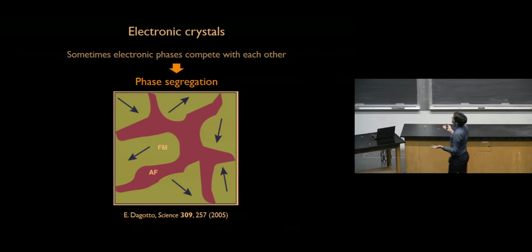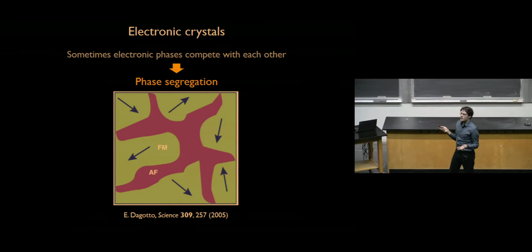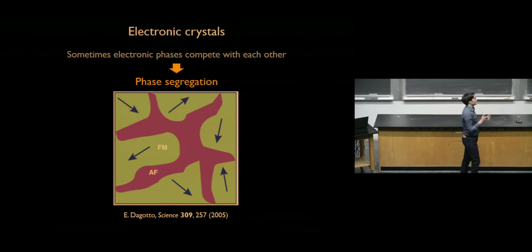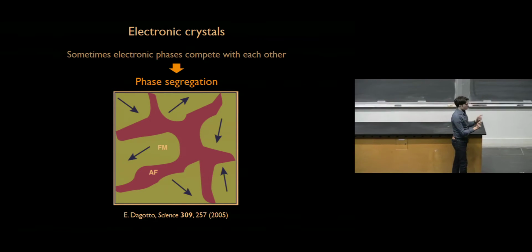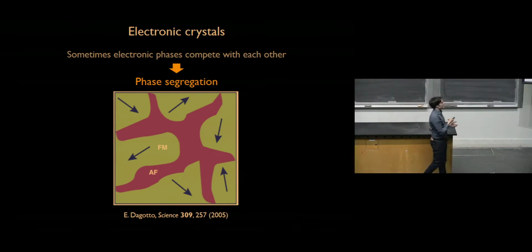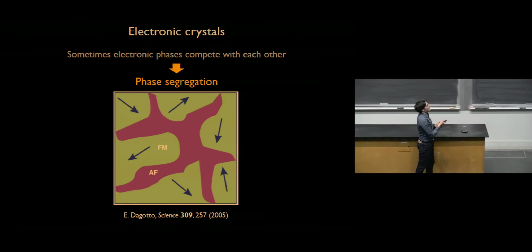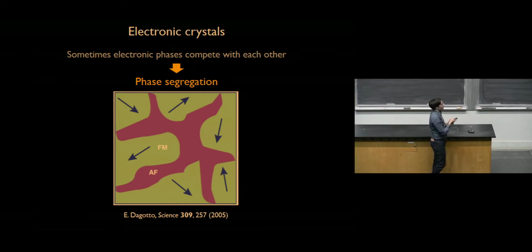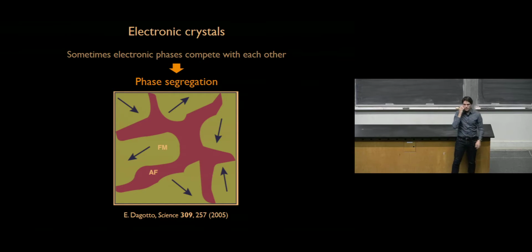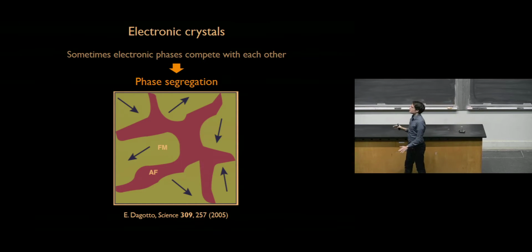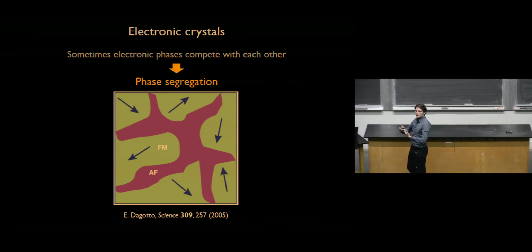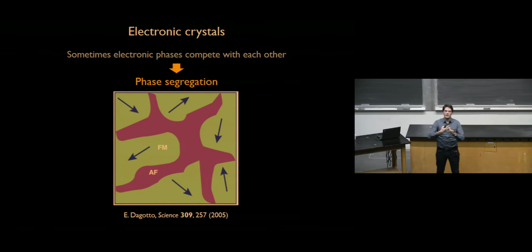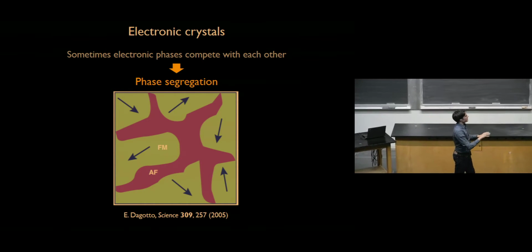So sometimes electronic phases compete with each other, and that leads to phase segregation. They don't like each other, but they also have very close energy. So what typically happens is that one of them will segregate in a spatial domain, and the other one will segregate in the other spatial domain. This is the case of, I think this is, again, manganites, where you have coexistence between antiferromagnetism and ferromagnetism. So they coexist, but they also compete. They don't like to be mixed together. They're not miscible electronic phases in a way, and so they segregate from each other.